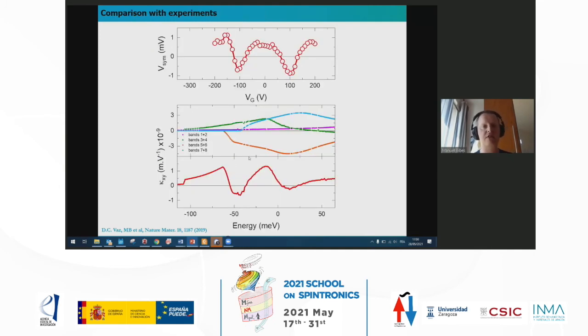And now you can compare the sum of these effects shown in red with our experiments. And you see that we have pretty good agreement with all the maxima and minima here. So we really are able to conclude that the complex energy dependence of the spin-charge conversion in the system, which can be really useful for devices, is caused by the unique band structure of this oxide two-DEG.